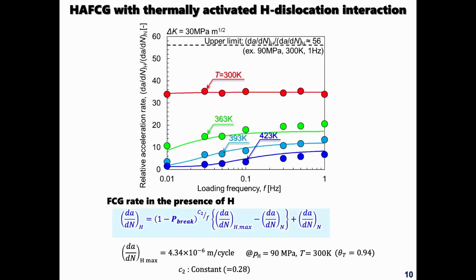So now we can define the experimental equations with the breakaway probability. This term, 1 minus P break, means the probability that dislocation cannot overcome and triggering the intense acceleration of fatigue crack growth. The curves for each temperature represents the fitting data to this experimental equation. So from these fitting results, we can understand the overall aspects of the hydrogen-assisted fatigue crack growth at several temperatures and loading frequencies from the viewpoint of the breakaway events of dislocation from hydrogen atmosphere. But I think this concept is probably able to be applied to the case with different gas pressure.